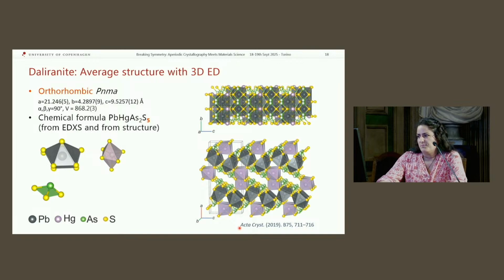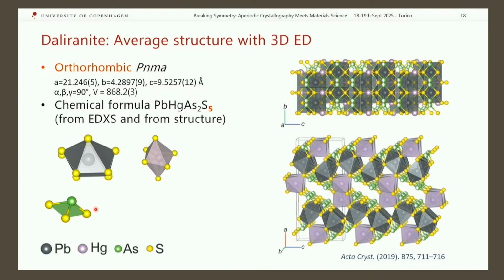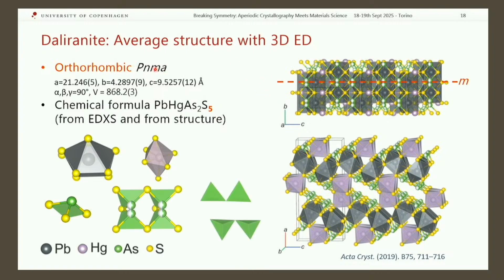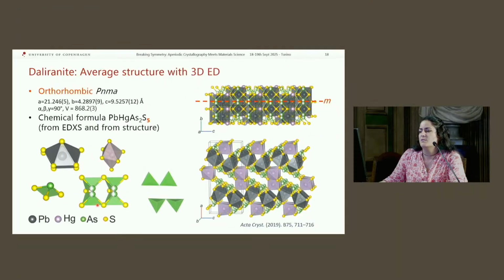So here we have an assembly of lead, bicapped trigonal prisms, some distorted octahedra of mercury, and then we have our arsenic that coordinates 3 sulfur atoms and forms trigonal pyramids. But you can see from the structural model here, something looks split, looks double, because actually in the space group symmetry there is a mirror plane, and these arsenic atoms are a bit frustrated because they are not at the suitable distance to coordinate both the sulfur above and the sulfur below at the same time, for example. So they have to choose, and they have to choose these 2 positions above or below the mirror plane. And this is the average structure, so we could say that this is disorder over the 2 possible sites. And in the structure, our pyramids can point up or point down, depending on the position that is occupied.